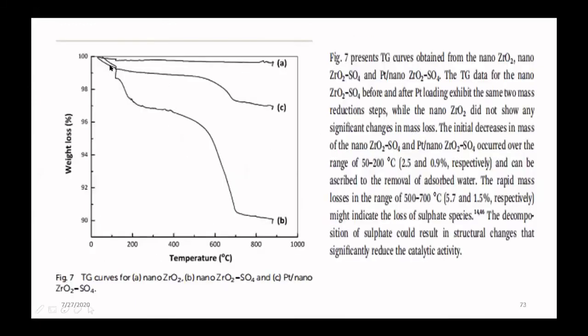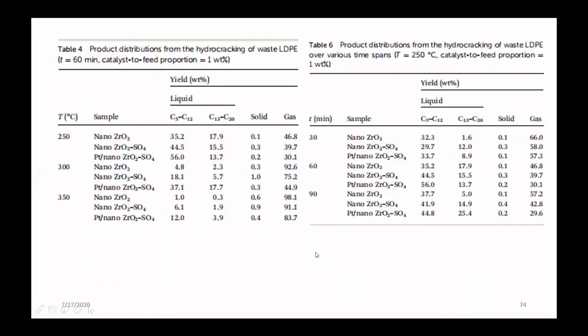This is a decrease in mass. From the GC, we obtain this product distribution of the material using various temperatures and various times, from the hydrocracking of waste LDPE. At 250, we obtain quite a good result; increasing the temperature decreases the gasoline fraction.